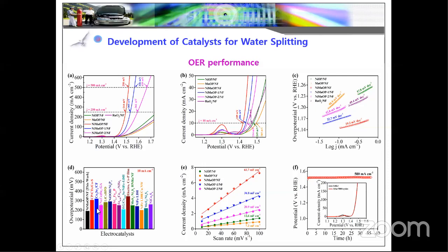We are also comparing with recent reports on transition metal chalcogenide based materials, and our material shows lower overpotentials. So our material is one of the best compared to the other reported materials. I already explained the BET surface area, and this is confirmed by the electrochemical surface area. When evaluating the surface area, the Cdl value should be measured in the non-Faradaic region. We also confirmed our material has a high surface area compared to the other materials, due to the hierarchical 3D ultrathin nanostructures.